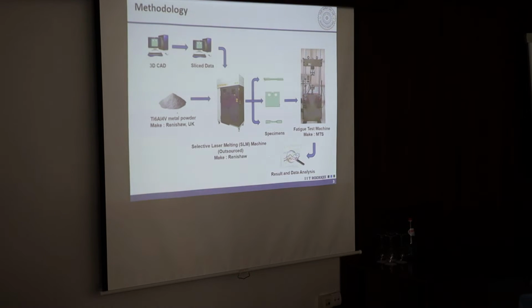So this is basically the methodology we have used. We fabricated three types of specimens: one is tensile, another is fatigue crack growth specimens, CT specimens, and the round specimens. We used a Renishaw AM400 machine for the same, and for fatigue testing we used an MTS 810, 100 kN capacity machine.